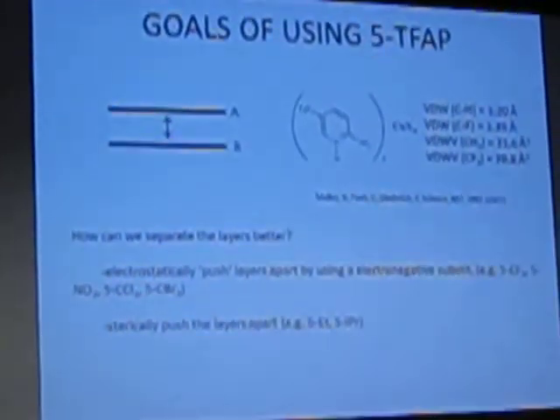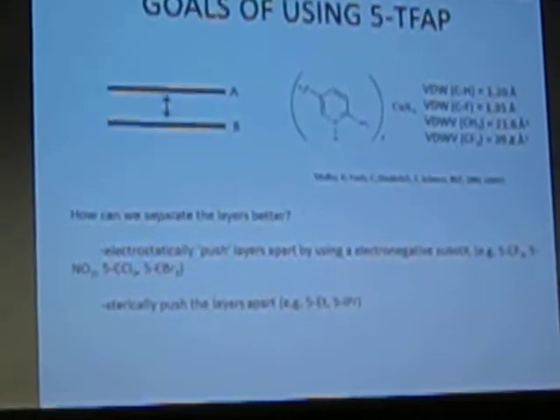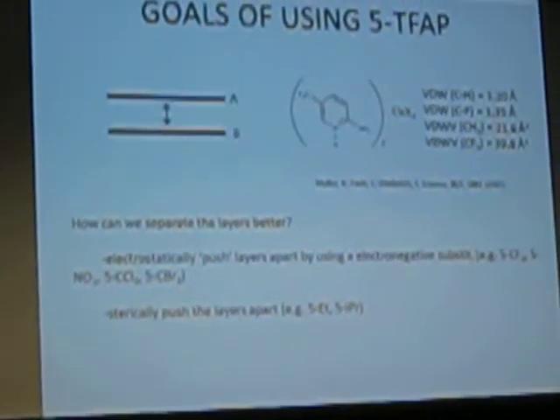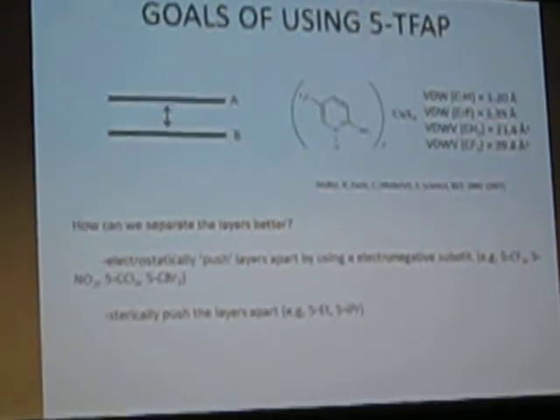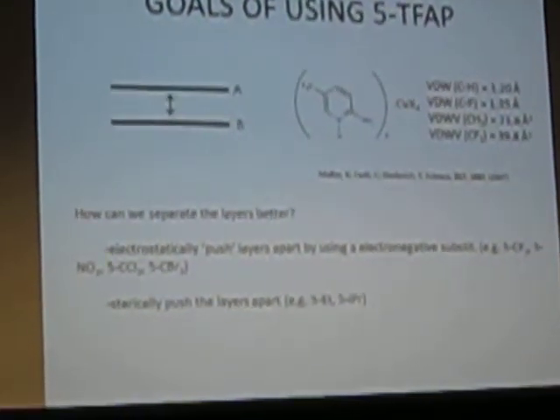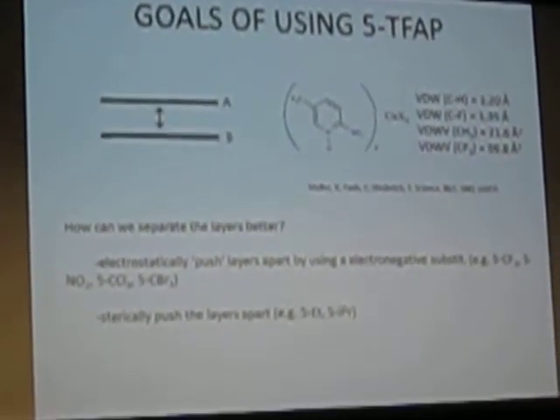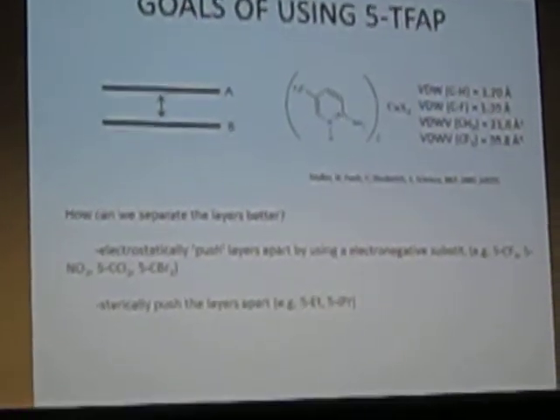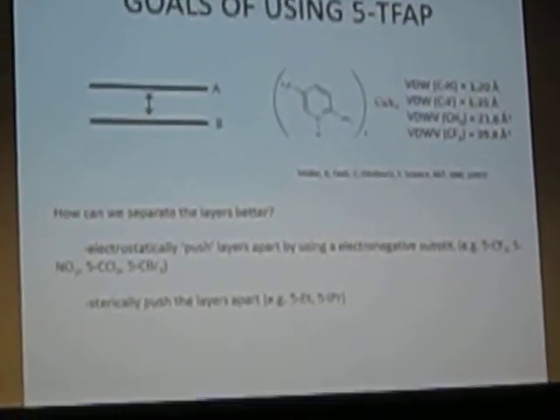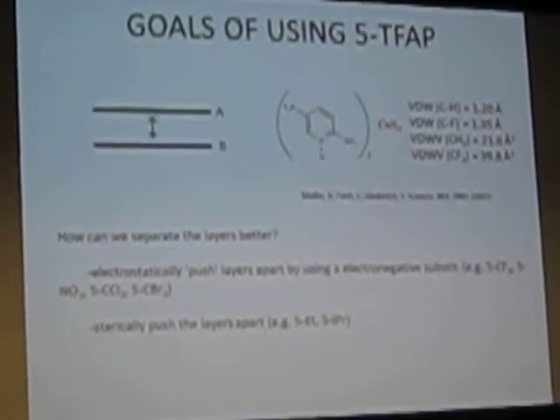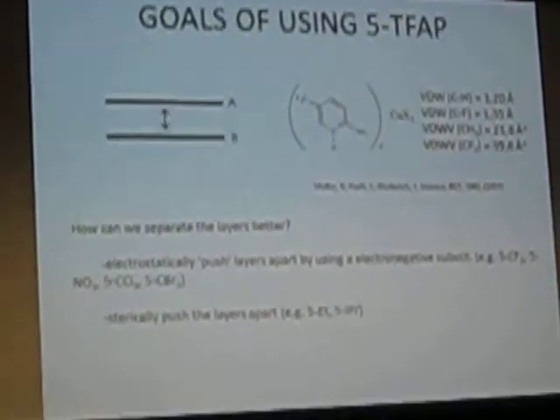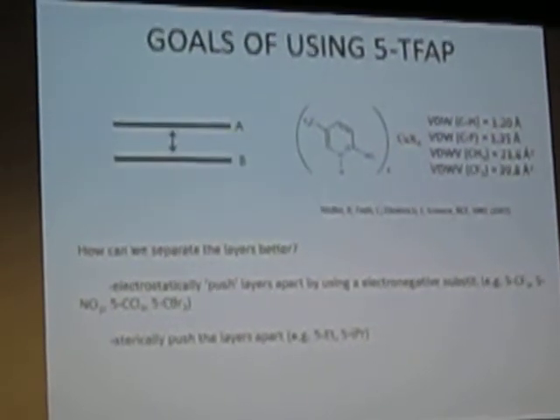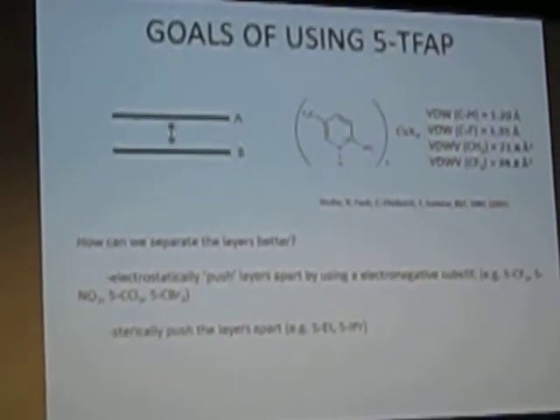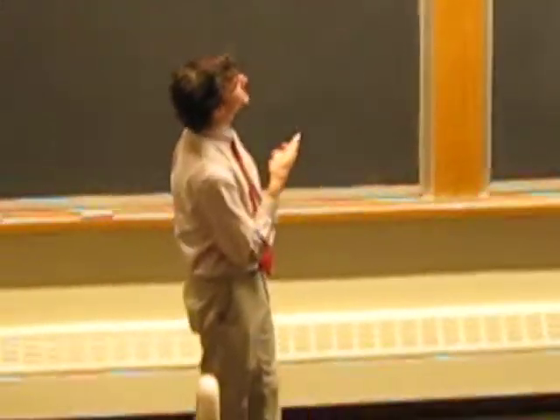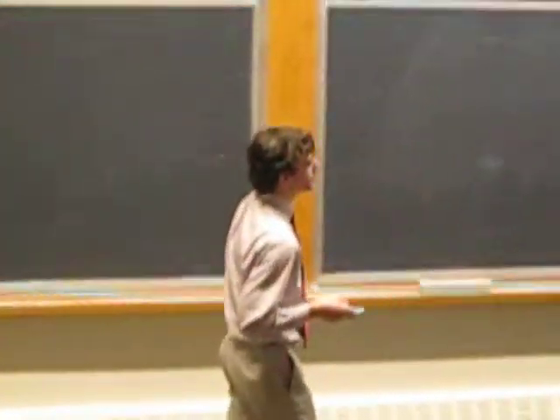So, with this goal in mind, we want to just manipulate the substituent here just a little bit. And we want to exchange the hydrogen atoms for fluorine atoms. Why are we doing that? The fluorine atom's van der Waals radius is about the same as the hydrogen atom. It's a little bit bigger, but the main thing that we're trying to affect here is the electrostatics of the substituent. So the idea here is we're actually going to push these two layers apart using electrostatic interactions.